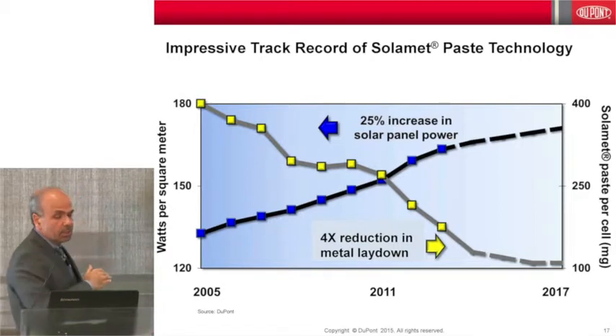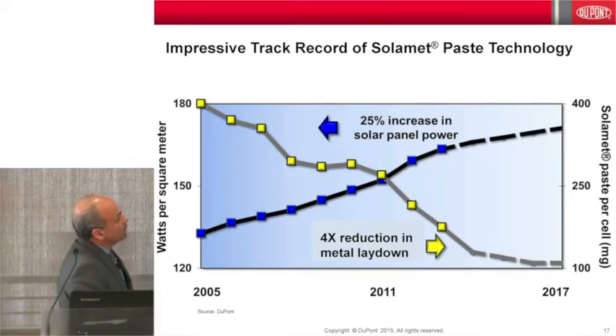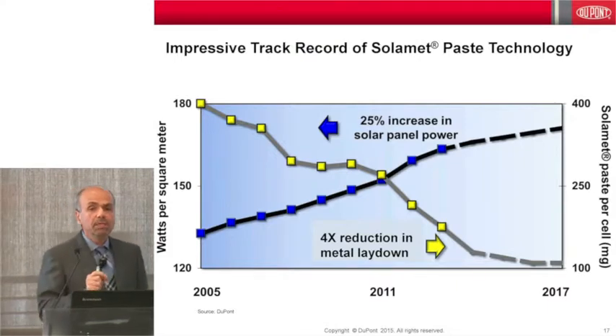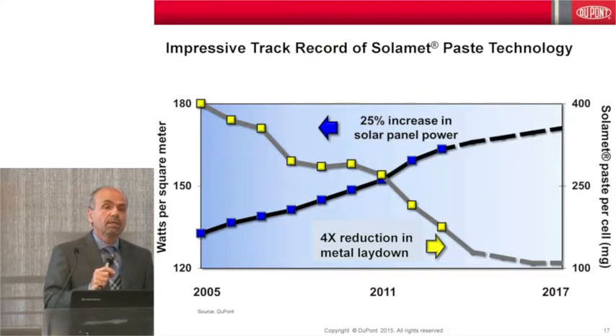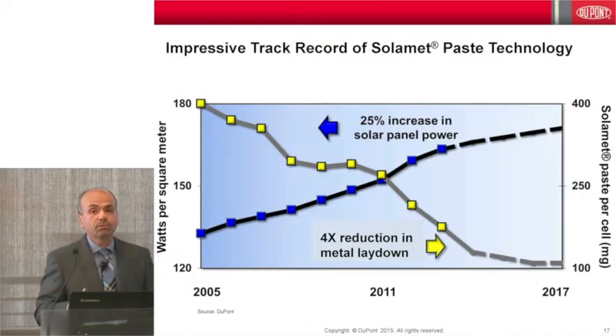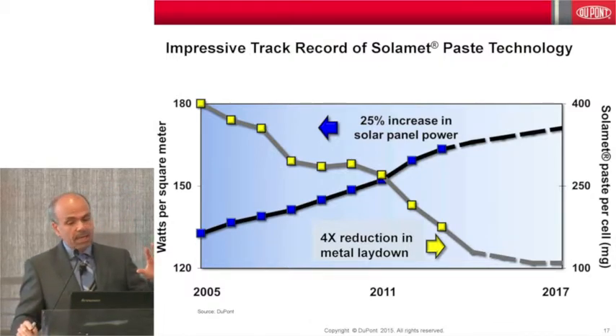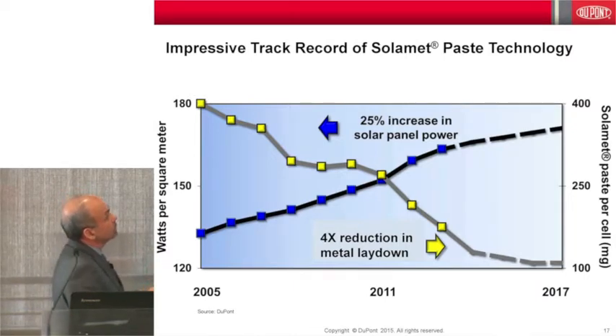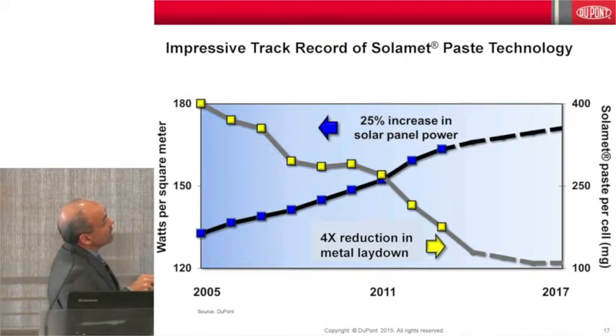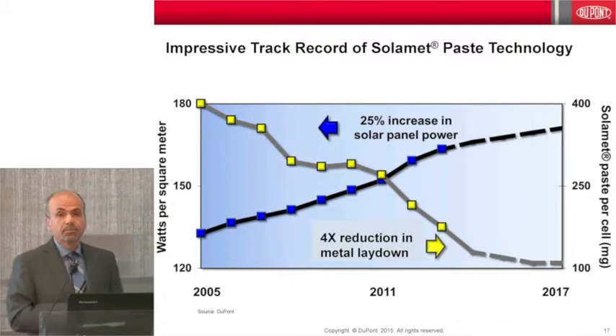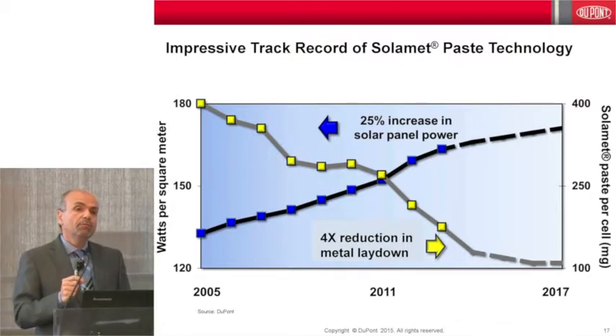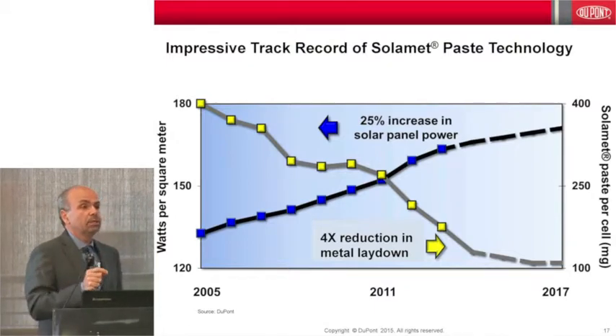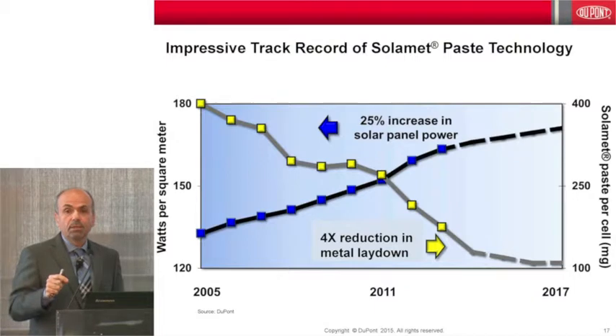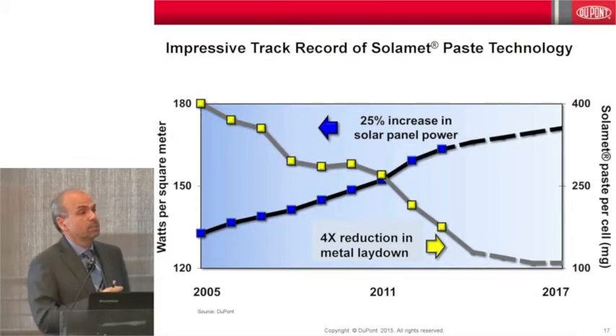So 10 years ago, we used to use about 400 milligrams of silver on the front surface. That, in combination with a very high price of silver, used to be a dark cloud on everybody's mind. And we have worked closely with our customers to reduce, as we call it, the lay down from 400 down to 100 pretty much in the past 10 years. Silver used to be one of the most expensive material components in crystalline silicon panels, and now it's not. The frame, for instance, or the glass is more expensive than the silver.